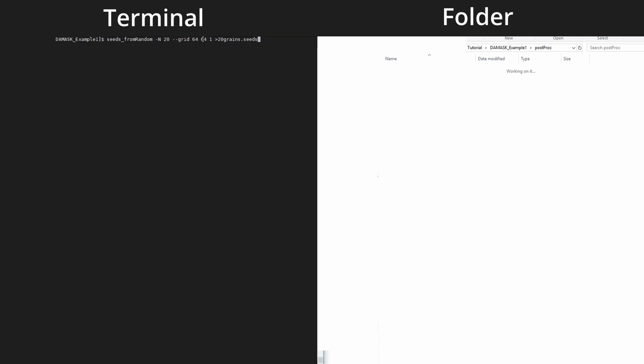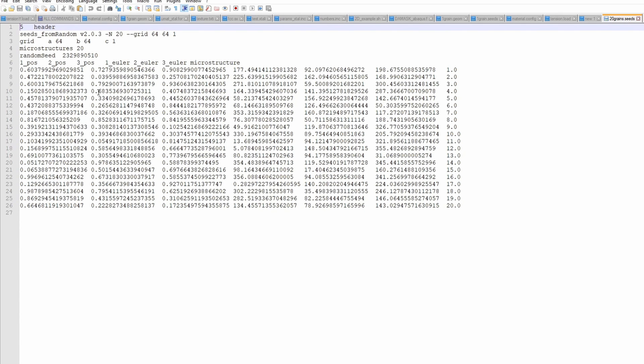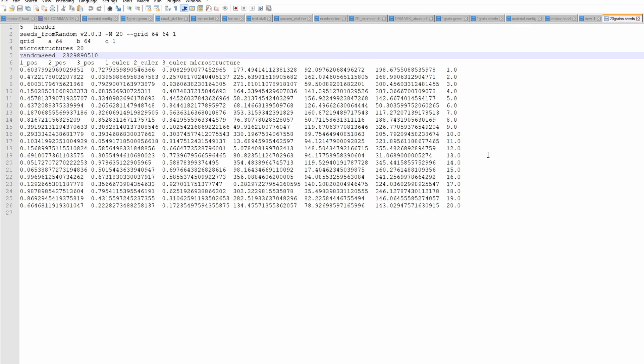We are using a 64 by 64 mesh, and the value 1 in the z-direction makes it 2D. If you want 3D, you type 64 there as well. This command creates a file called .seeds. If you open this file you will see 20 different seeds, each with 3 Euler angles representing the seed locations and orientations.